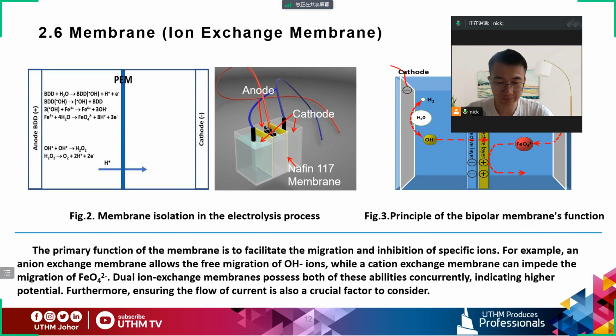The sixth factor is the membrane, the ion exchange membrane, in the electrochemical synthesis process. To prevent the diffusion of ferrate generated at the anode to the cathode for reduction, a membrane is introduced between the anode and the cathode of the reaction. This membrane not only needs to handle the diffusion of ferrate, but also must permit the flow of electric current and the exchange of the necessary ions.